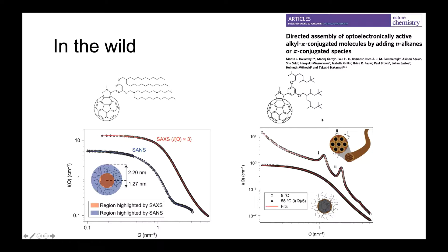By changing the ligand, they were actually able to achieve a hierarchical structure. At higher temperatures, you would get that core-with-ligands structure. But as they reduced the temperature, this core-ligand structure would self-assemble further into a lamellar structure resembling a fiber. Using SAXS, they were able to observe different signatures — one peak at q and another at 2q. Using SAXS in situ, they were able to observe this structural transformation on the mesoscale, which is pretty powerful.